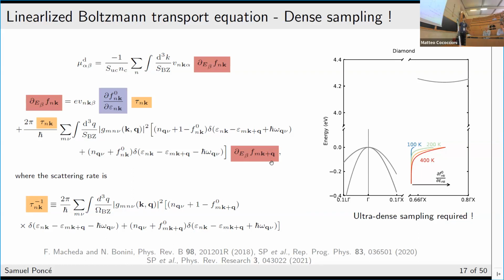The EPW code can read an interatomic force constant. So if you're doing SSCHA or TDEP or whatever, you can simply get your renormalized or changed phonons and plug them in there. Now, if you want to go beyond, and this is not done yet, you can also express this theory in a Kubo-like form in which you have spectral functions. In that case, you can plug in spectral functions both for the electrons and for the phonons inside your formula, and that can be very important if you have strong anharmonicity, where the phonon modes are not very well defined and you have a sort of crosstalk between all these phonon modes. One easy way is just to use the spectral function, because then you have very dispersive bands, and they can talk to each other when you do the integral. So those are directions to go, let's say.